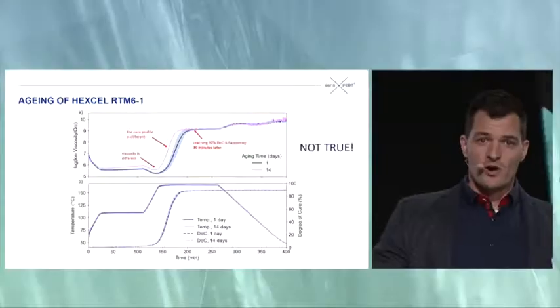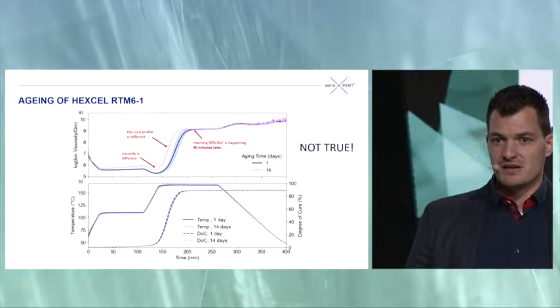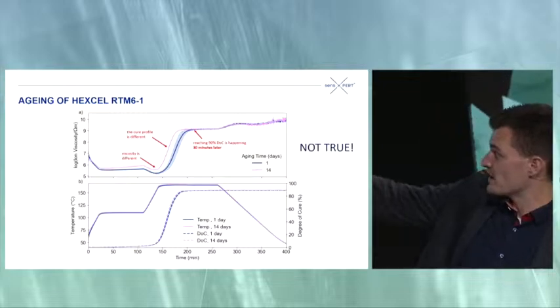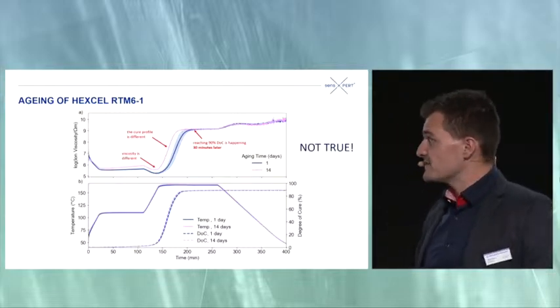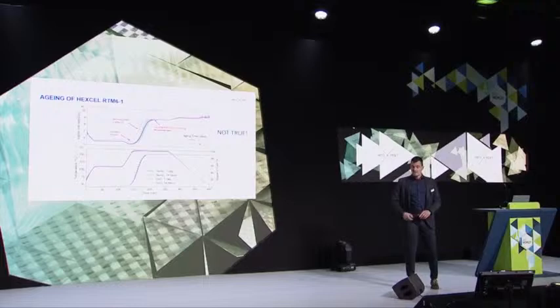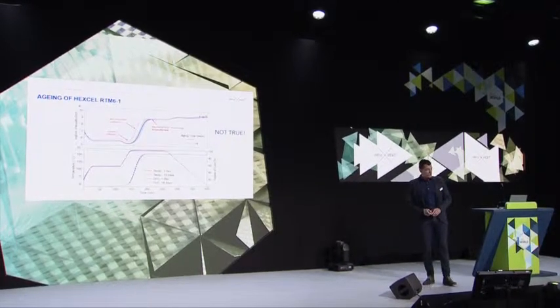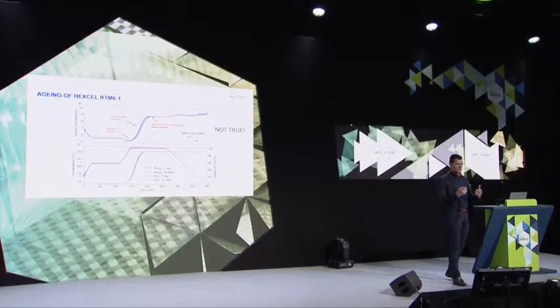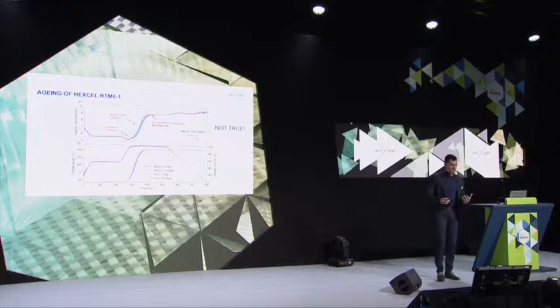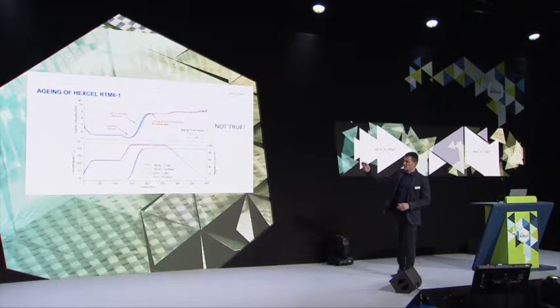You can see the viscosity behavior is different, so the older the material, the higher will be the minimum viscosity during production. Even the pre-curing at this infiltration phase is visible more and more. And you can see that the older material cures faster because we have a lot of solvents within the resin that can degas during the procedure of storing it at room temperature. And that is why the system cures faster. Even the inhibitors blocking the reaction are a little bit weaker with the older material here, because the inhibitors will get destroyed from time to time.